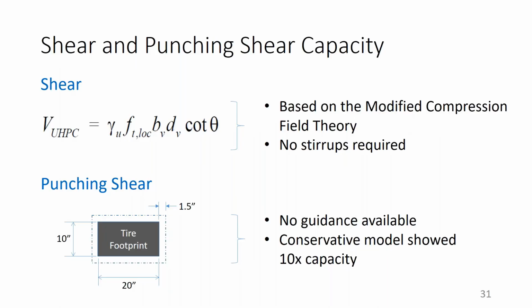Now, there were questions in the set of questions we got earlier on about shear and punching capacity, and I had those in before. But look at the equation for shear. This is from the FHWA guidelines. You will recognize the B times D, right? That's the cross-sectional area. You might recognize the cotan theta from first principles, although this is based on the modified compression field theory. But what is odd and weird is that it's based on FT localization. That is the tensile strength of the material at the localization strain with another factor attached to it. So basically, you are relying on the capacity of the fibers to give you the shear capacity that you need.